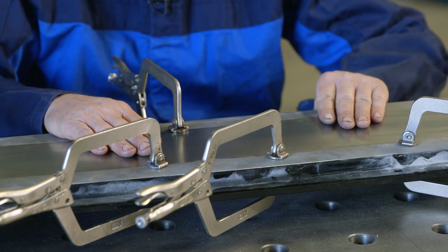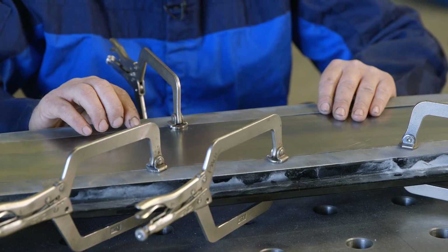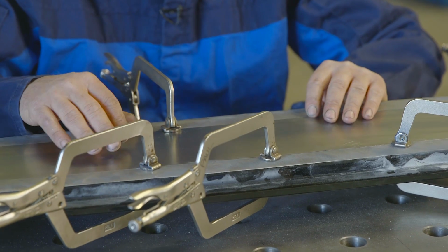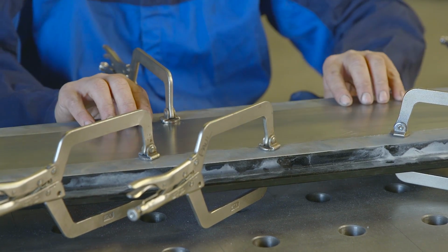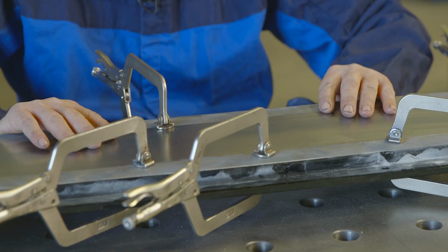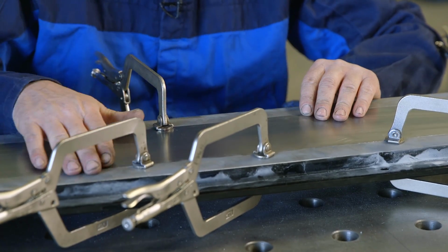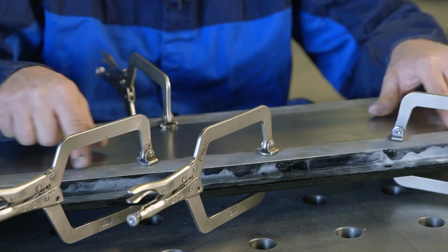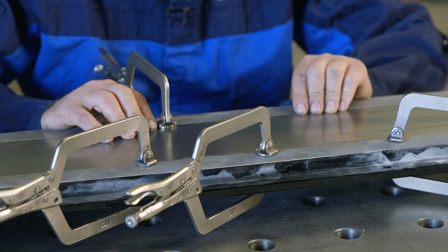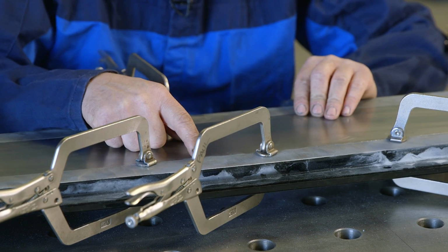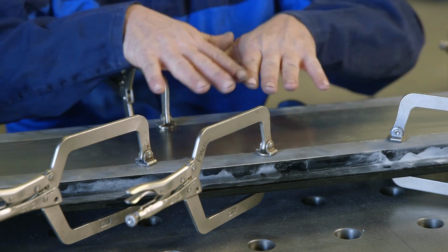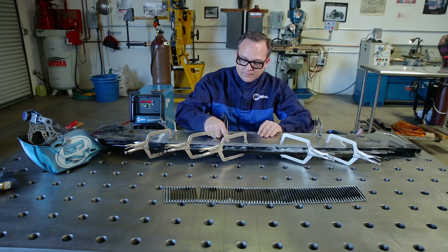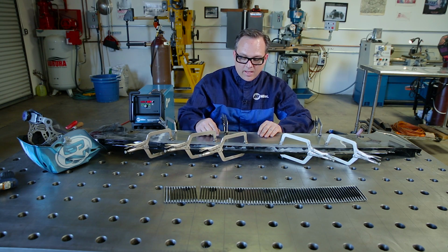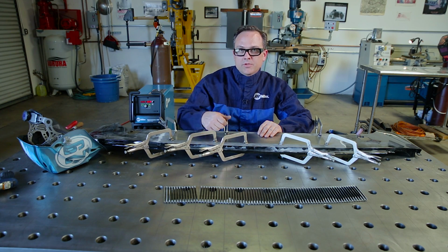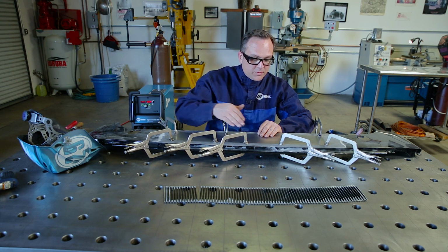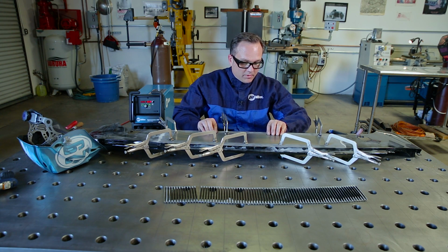So I now have my new panel cut out, and I have fit it really tight by filing the edges to make sure that it fits perfectly, and it's actually taking the shape of the cowl as it sits here even. I use lots of clamps to hold it in place so I can make sure all my joints are really tight, because we want these joints as tight as possible and to hold its shape while we tack. That way it doesn't warp when we're finished. And to get that, I hand filed, and I had actually hammered some of the edge where I was cutting with the snips to make sure that it's nice and flat and smooth. So it seems like it's fitting very well right now.